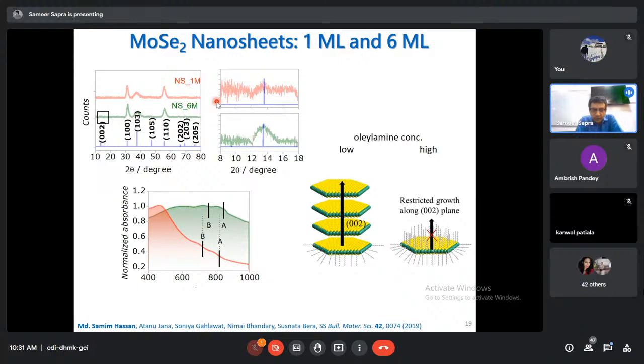For example, over here, I can show you data from one monolayer nanosheets and six monolayer nanosheets. And if you look at the XRD pattern and focus on the 002 peak, you'd see for one monolayer, there's hardly any intensity.